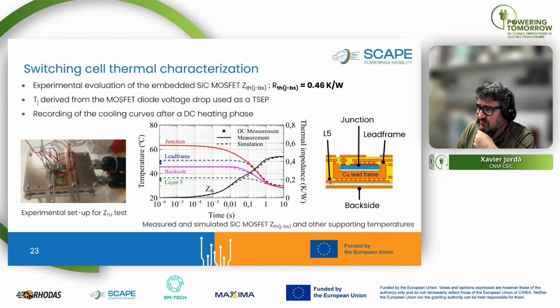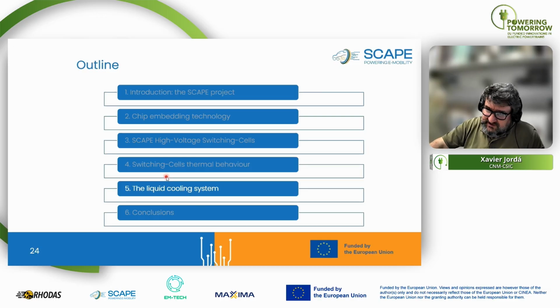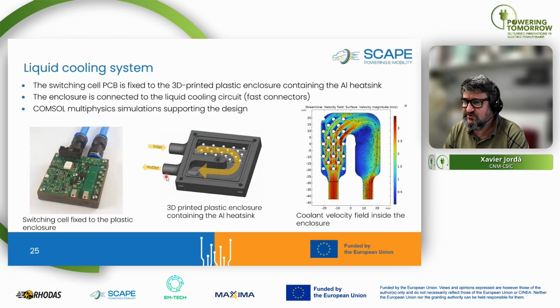Let me also mention that we have used auxiliary thermocouples inside the chip embedding stack in order to have additional information for tuning these simulation parameters I mentioned before. Concerning the thermal response from the backside to the coolant, we developed this kind of enclosure, as I mentioned before, which forces the coolant flow, and which also contains the aluminum heatsink that spreads the heat generated in the switching cell and improves the heat exchange with the coolant.